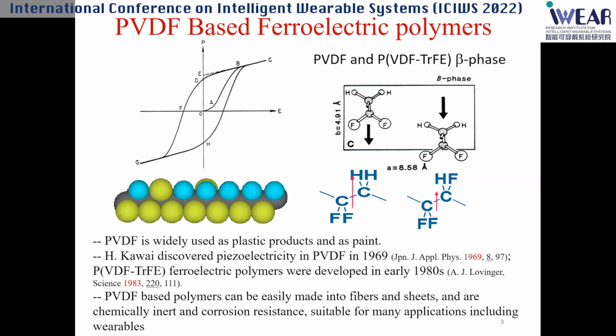It took another 10 years for this PVDF-TrFE polymer to be developed, as reported in this 1983 Science paper by Lovinger. It basically expands this VDF to TrFE, which has a little bit larger size, and its dipole is half of the VDF. But even with that, the performance of this PVDF-TrFE copolymer is actually better than PVDF, and therefore it greatly expanded the application range of this material, including in many wearable devices, if you look into the literature.